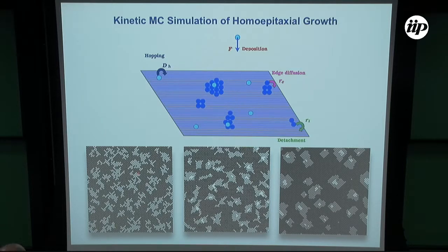This is another talk, of properties of these islands. They're very useful in the experimental realm in a sense that they can be used as quantum dots because electrical and optical properties of these islands are very different than the bulk property, and you can freeze them, but as I said, by depositing another type of atom on top of them and using these thin films for particular purposes. But this is not really the purpose of my talk. The purpose of my talk is to talk about what happens when you deposit many, many layers. I want to talk about evolution of morphology when many layers are deposited.